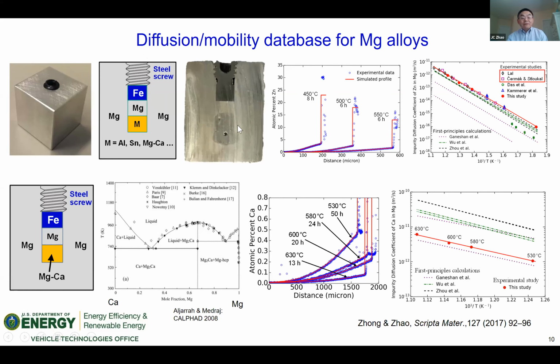So this is big enough that the liquid will just be contained in the middle. And if you do the measurement, you get a diffusion gradient in the solid solution. So we can measure the solubility limit very, very accurately. And then we use forward simulation analysis, and we were able to get the impurity and the interdiffusion coefficient. So we tested this on zinc diffusion in magnesium. You can see some of those data were tracer data, and the red dots are our measurement. You can see how accurate that is.